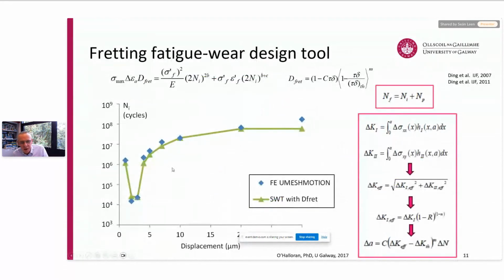And then we've implemented that with a fatigue damage model, which is the Smith-Watson-Topper model that Alex spoke about earlier, which is an established high-low cycle fatigue model. It combines high and low cycle fatigue, and also includes the effects of mean stress. And in this particular case, we've included some of the aspects that Alex spoke about, in particular the critical plane aspect, where one tries to apply a Mohr's circle type stress and strain transformation to identify the worst critical plane or orientation for this parameter. But another key aspect we've included is this fretting damage term, which we previously developed in the work of Ding et al., when I worked at the University of Nottingham. I think Phil was involved in that work as well, actually.